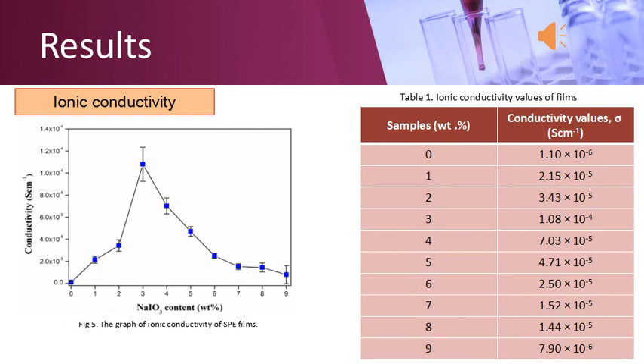It can be seen from the figure that the ionic conductivity of the SPE film starts to increase until it reaches the highest value, which happens due to the decreasing value of bulk resistance. But then it starts to decrease after additional sodium iodate content in the electrolyte. This behavior may be affected by overcrowding of ions, which can be attributed to the formation of ion aggregates. Besides, the bigger size of contact ions formed will limit the movement of ions in the SPE, so the free mobile ions will decrease, as well as the number density of free mobile ions. Hence, the conductivity will decrease.